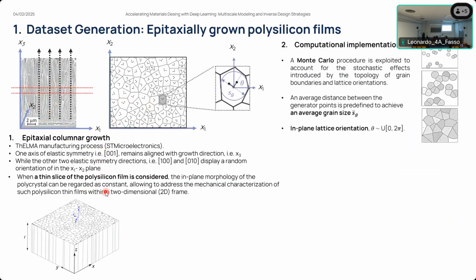In order to reproduce this kind of morphology from a computational implementation, we perform a Monte Carlo procedure, which is exploited to account for the stochastic effects introduced by both the topology of grain boundaries and also the lattice orientations. Particularly, an average distance between the generator points when we are performing the tessellation is enforced in order to achieve an average grain size that is characteristic of the specific manufacturing process that we are characterizing in this case. On the other hand, the in-plane lattice orientation is regarded as a random variable that can take values in between 0 and 2 pi in the plane.